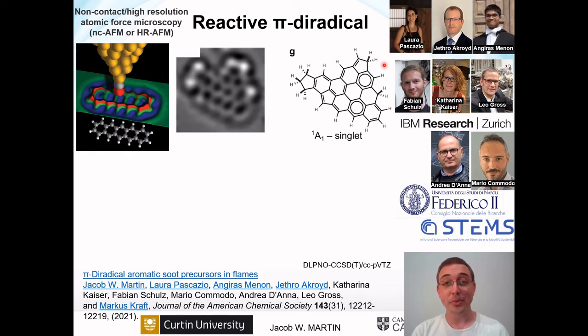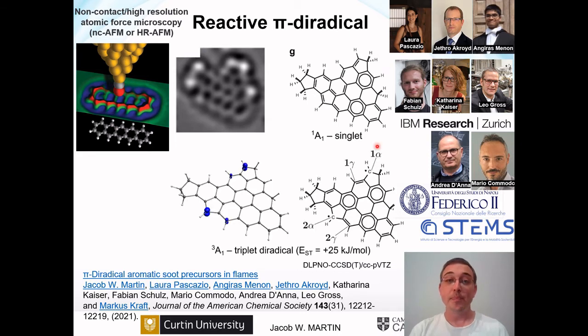But to our surprise, when I computed the electronic structure at a reasonable level of theory, I found that the electrons like to not pair up to form a diradical species, so a triplet diradical, where the two radical sites are considerably reactive. And this really demonstrates that these localized π-radicals are indeed localized to the edge because they're not able to bond through the aromatic network. And this makes them very, very reactive, these triplets.